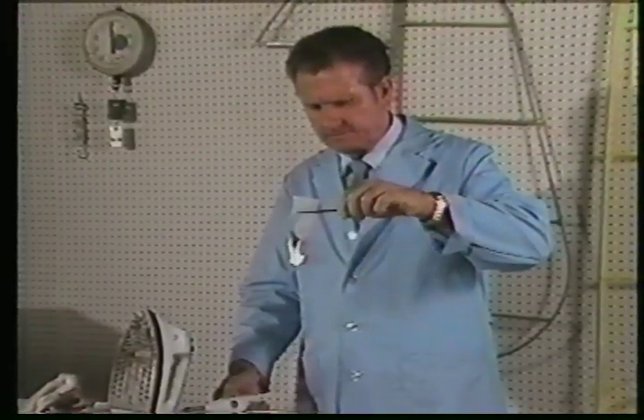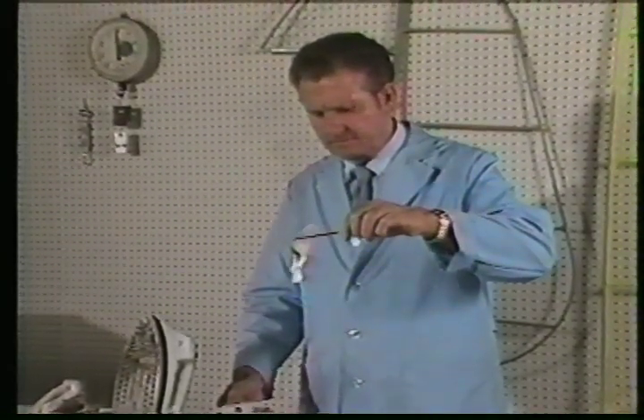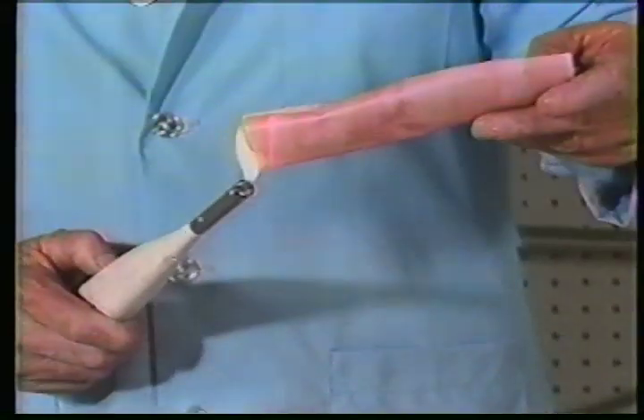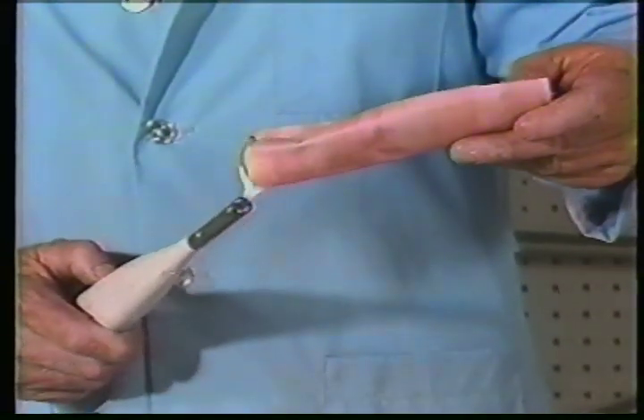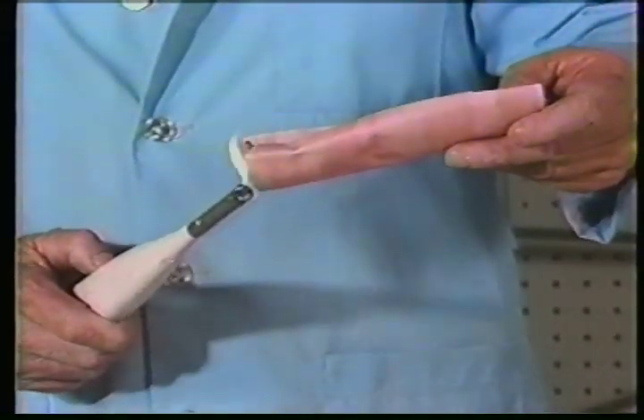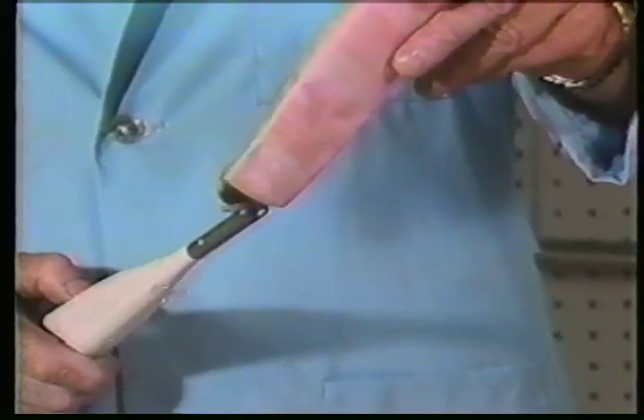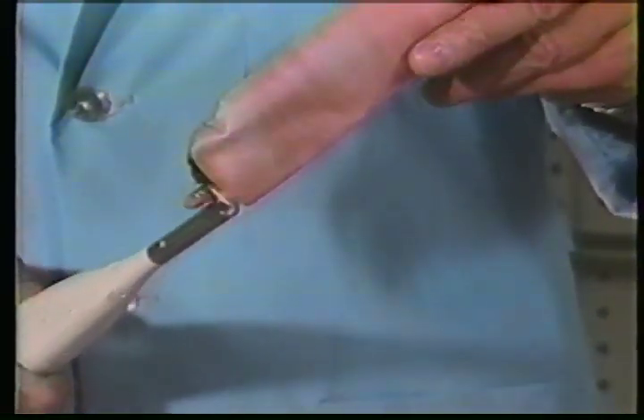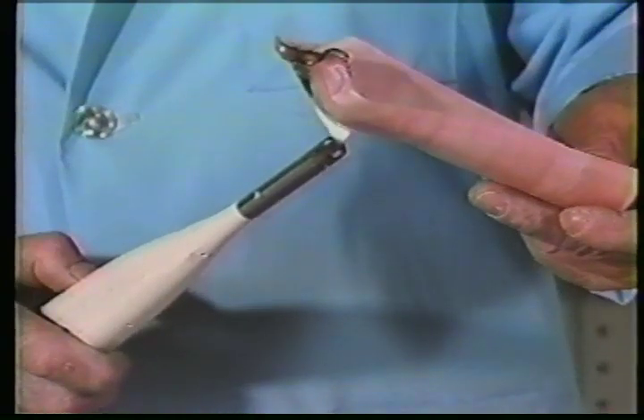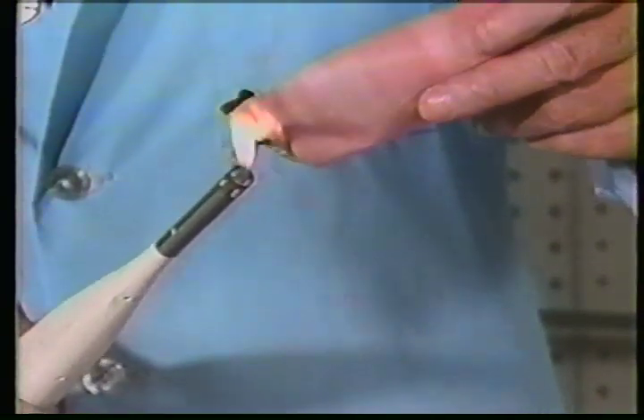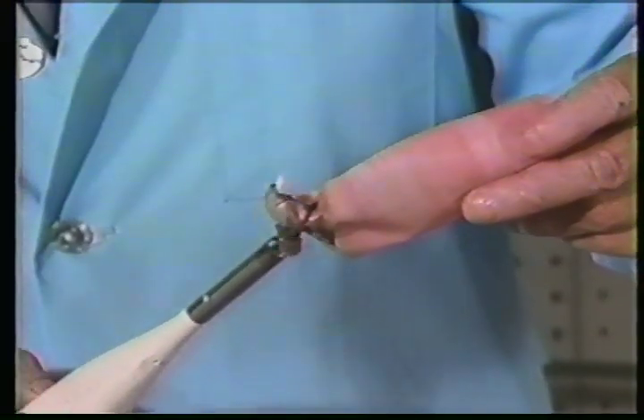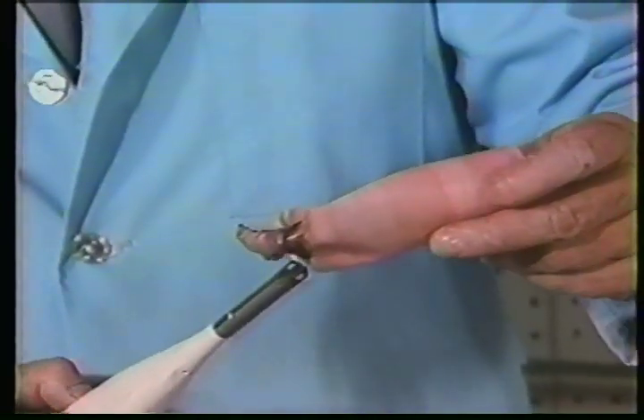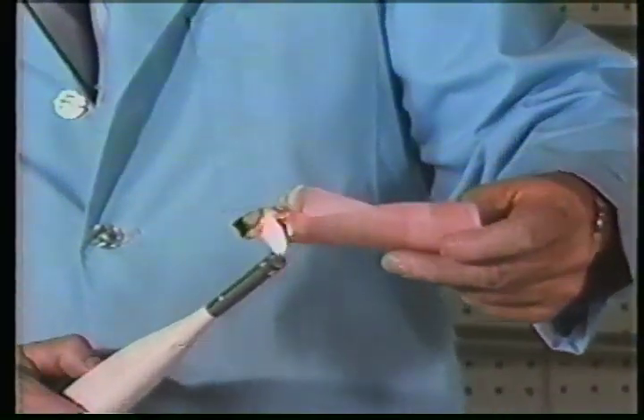We have already seen that bare polyester fabric will continue to burn. This is a sample of polyester fabric with just 2 coats of Polybrush. The fabric will melt. However, when the fuel source is removed, the fire is extinguished. We frequently receive reports from people who were flying aircraft covered with Polyfiber materials and survived an accident involving a fire, which did not spread.